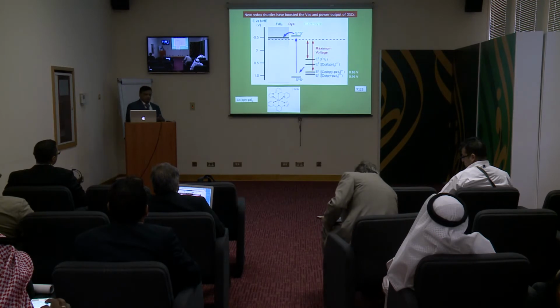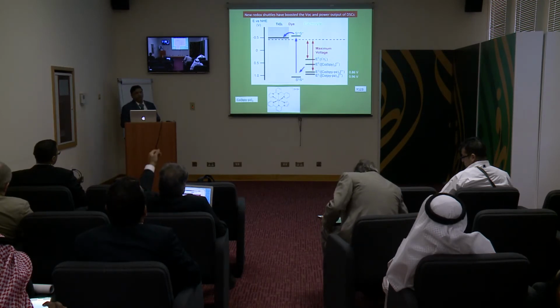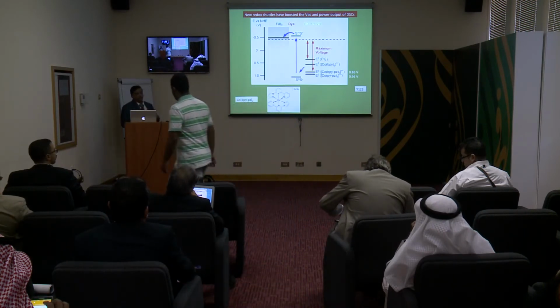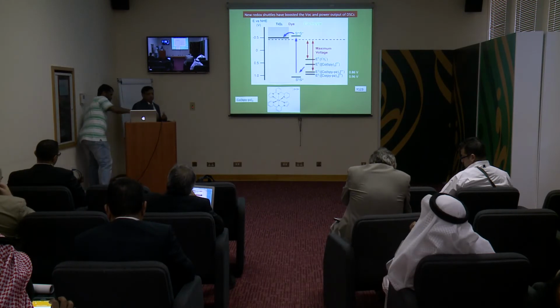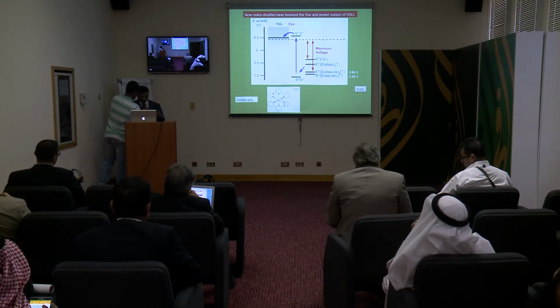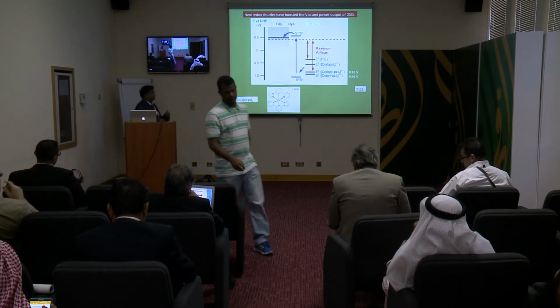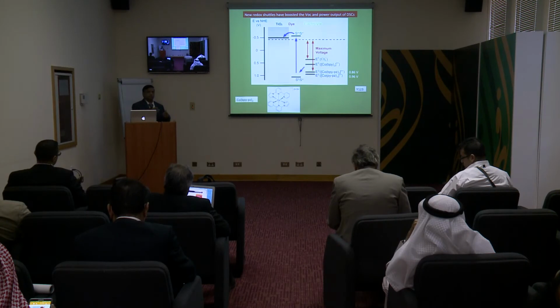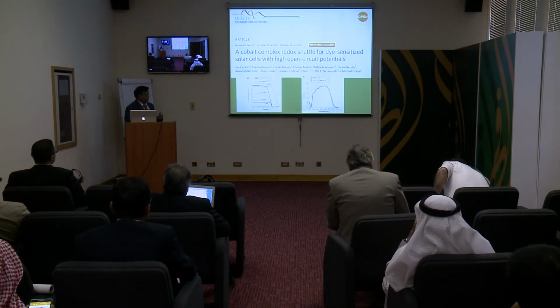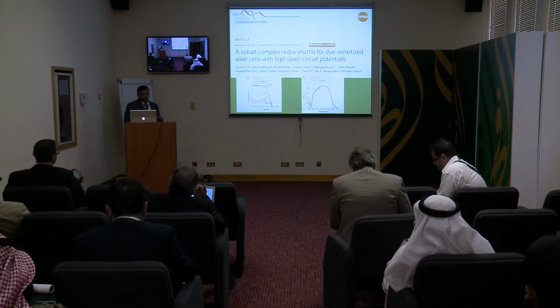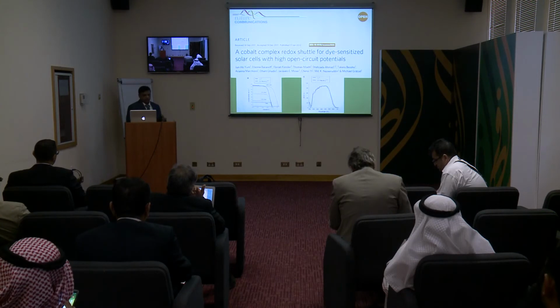For example, as I said, you cannot tune the redox energy of the iodide electrolyte because it's fixed. Whereas in the case of cobalt complexes, depending upon the basicity of the ligand, you can tune the energy of these cobalt complexes, and then you can fix at what range you want to have this energy. So depending upon the HOMO level of the sensitizer, you can tune the energy level wherever you want. So that can contribute to increasing the performance of the devices. So this is how one can go to 1 volt of open circuit potential by tuning the right ligands on the cobalt complexes to get high performance.